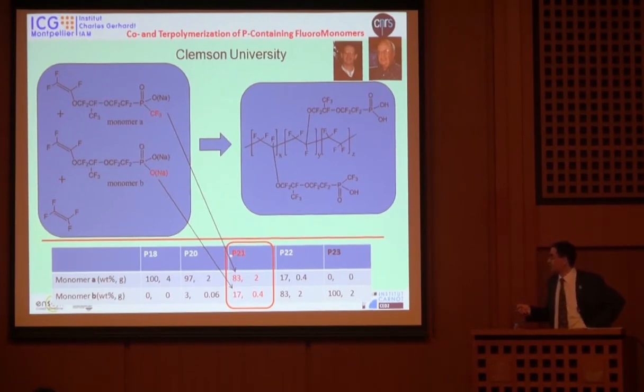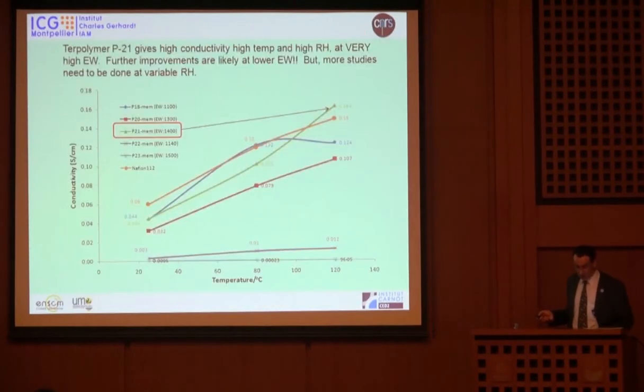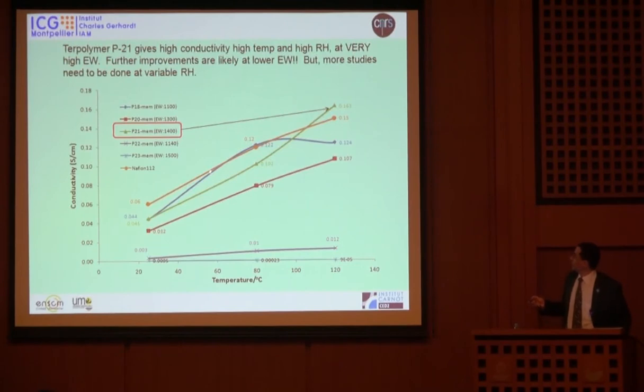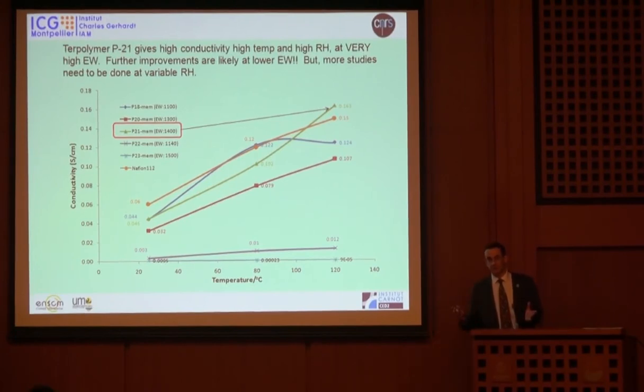And when you see this polymer 21, as called by this group, you have a very nice compound. And this enables, when you study the conductivity versus temperature, to have very nice results. Here, the green part is a polymer containing this phosphonic acid, showing a higher conductivity than that of Nafion. Nafion is the orange curve. So always, when you measure conductivities, try to compare with Nafion.